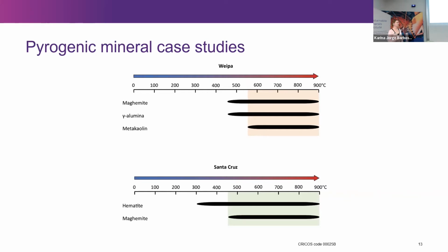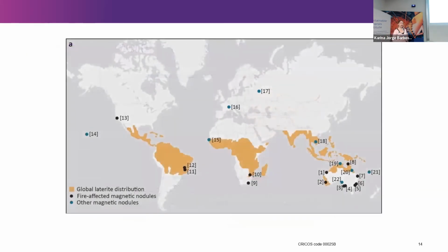And similarly for Santa Cruz, the highest temperature mineral I have here is maghemite, so the lower bound's at 450 degrees, and again, upper bound at 900. And this is quite interesting going forward.